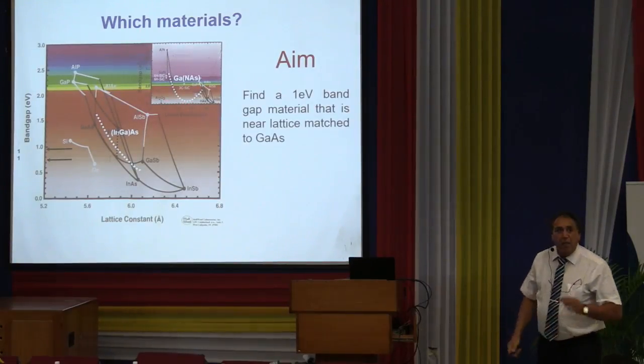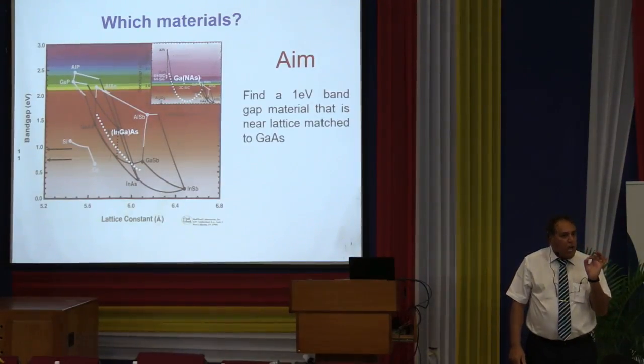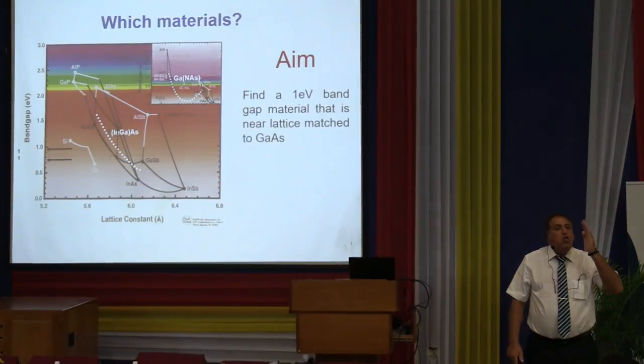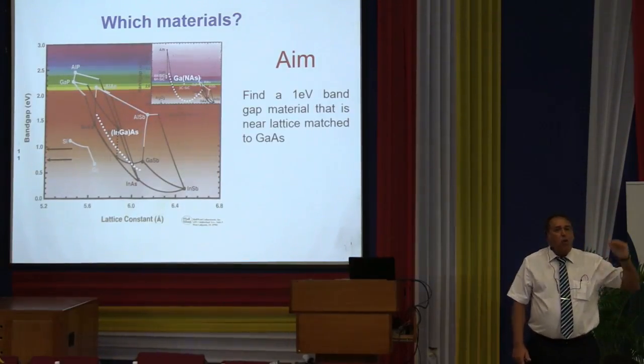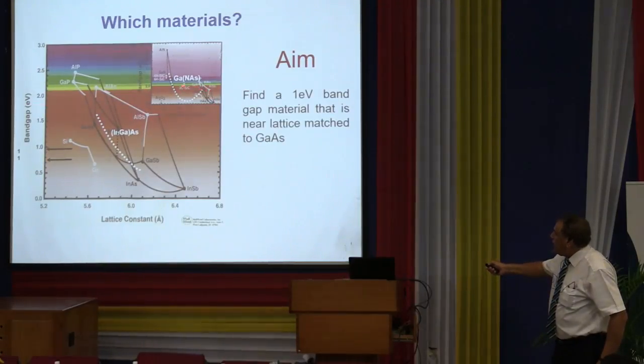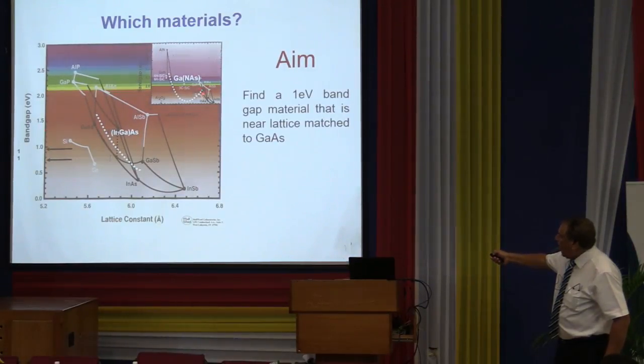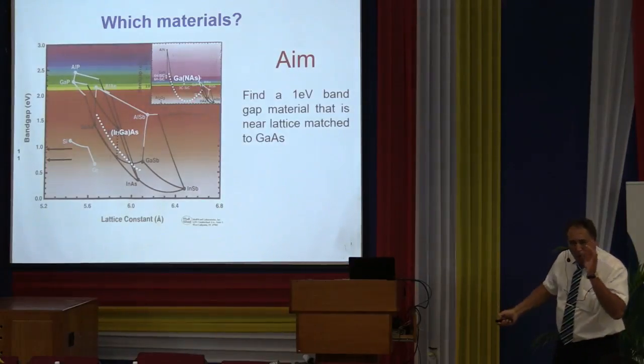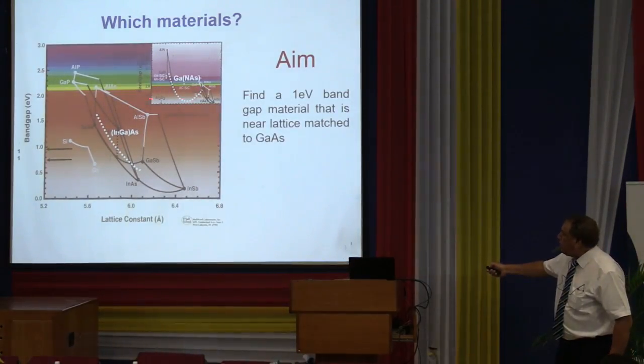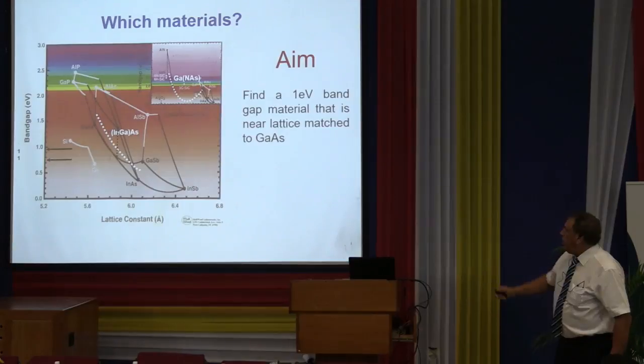This material system actually decreases before it starts increasing. By putting a small amount of nitrogen into this gallium arsenide, the energy decreases first. The energy of gallium arsenide is about 1.4 electron volt. So by adding a small amount of nitrogen, I can decrease it and reach 1 electron volt. That's what I'm aiming for, right? 1 electron volt, before it increases.